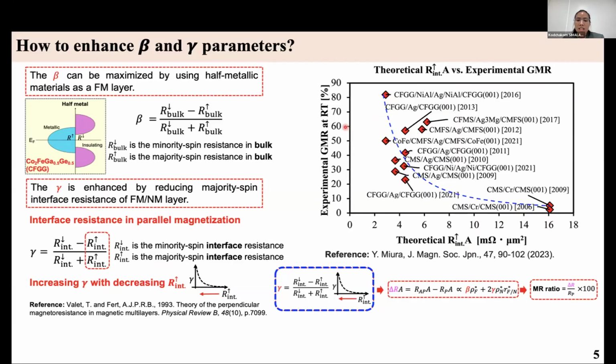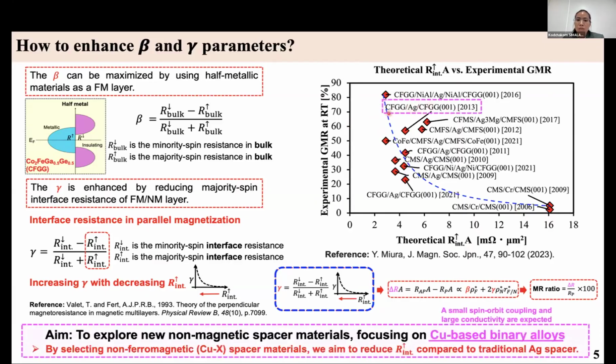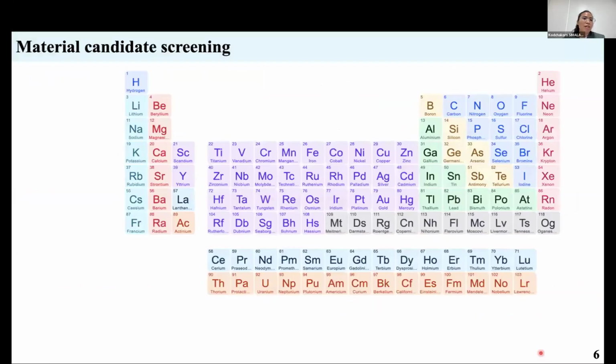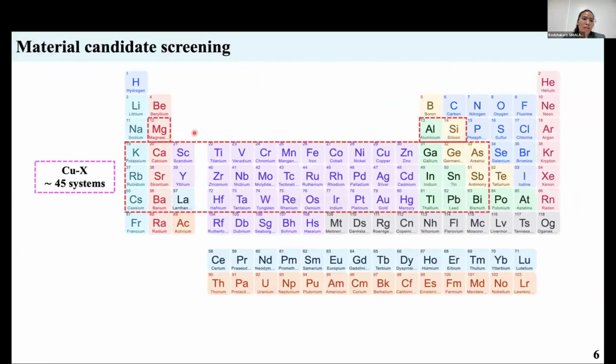And in the previous study, they found that using the Ag spacer with the CFGG electrode provides a high MR ratio compared with the other single crystal spacers. Consequently, the aim of this research is to explore new non-magnetic spacer materials, focusing on copper-based binary alloys, because in this kind of material, a small spin-orbit coupling and large conductivity are expected. So by selecting the non-ferromagnetic Cu-X spacer materials, we aim to reduce the majority spin interface resistance compared to the traditional Ag spacer.